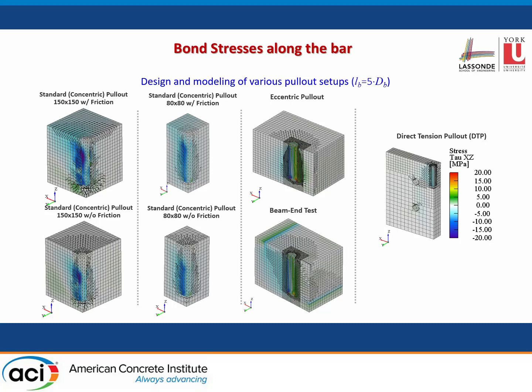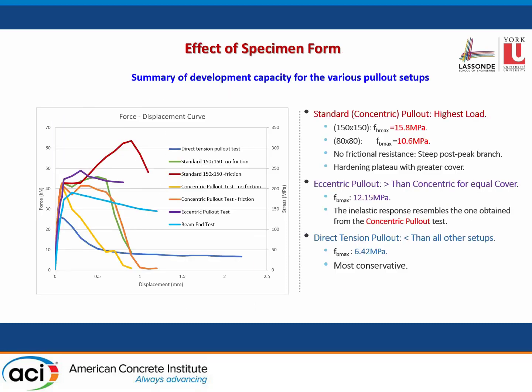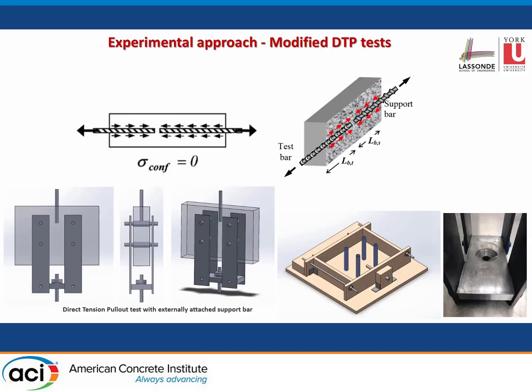So the outcome of this preliminary analysis, done in order to conclude which specimen form we would use, showed a significant scatter of calculated results in terms of bond capacity of the bars that illustrate the spurious effects of the various test setups that are routinely used to characterize bond. The lower curve is the one that corresponds to the direct tension pullout, which is now used for the experimental study that follows.